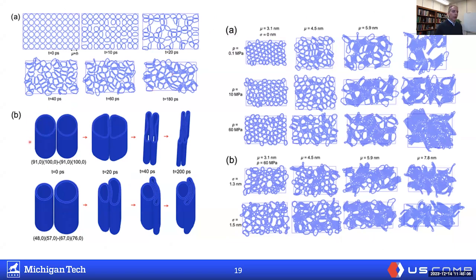For example, a model like this would tell us that two carbon nanotubes beside each other, when they do flatten, they'll flatten very nicely in this array. However, if their diameters mismatch, then we don't get quite the type of efficient packing that we want. And by controlling the diameter of the nanotubes, controlling the distribution of diameters of the nanotubes, and controlling the pressure involved in manufacturing, which Nanocomp can control, we can actually look at how these yarn geometries form, how the morphology of the carbon nanotubes form, and how we can control that. And if we know this, we also know their predictive properties. And so this is a really good way that we can use computational modeling to help adjust processing parameters to help drive the material development.